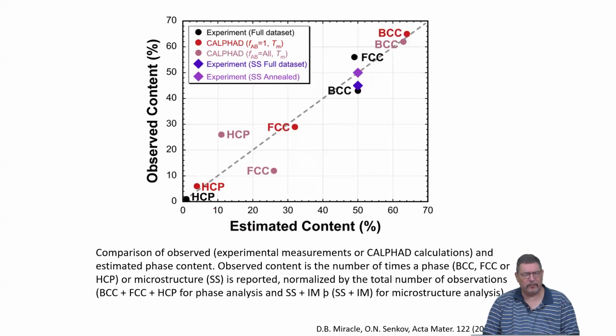And this is also confirmed if we, for example, look at the comparison between experimental observations of phase content and estimated content. Observed content means either experiment or Calphad simulations, and estimated content is this structure in, structure out approach, which you can do in experiment, but which you can also do based on Calphad calculations. And you see that basically this grayish line is lying in between these different data points. And here for Calphad, there are two sets of data given. There's this factor FAB equals 1 or FAB equals all.